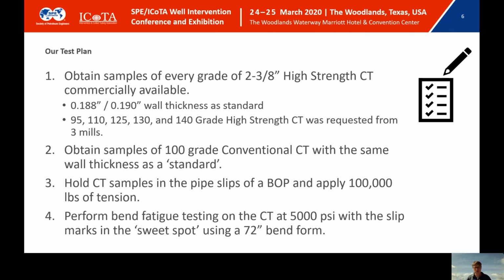The authors went back and forth on the best way to get this accomplished. Our thoughts were that if we went with 188, 190 wall thickness, that should be pretty available. We wanted to get samples in 95, 110, 125, 130, and 140 grade quench and tempered coil. We also wanted some samples of 100 grade conventional coil that we could use as our standard to compare to. The plan was to hold the coil in a set of pipe slips in a BOP